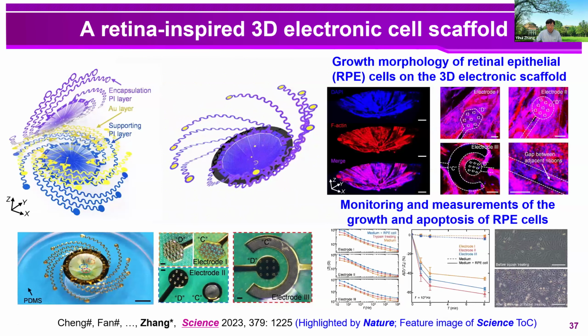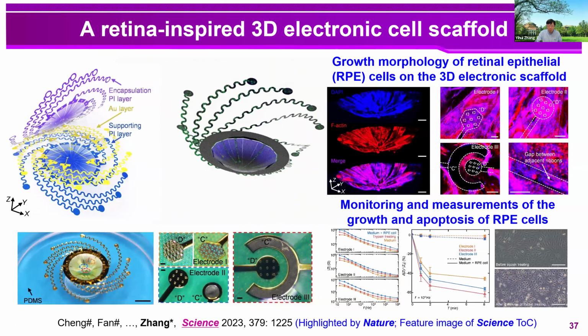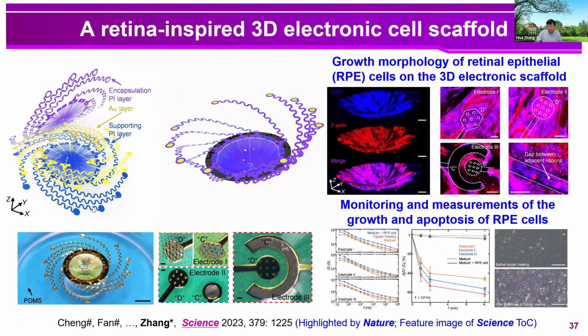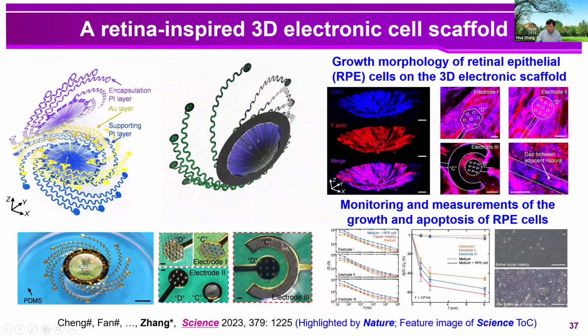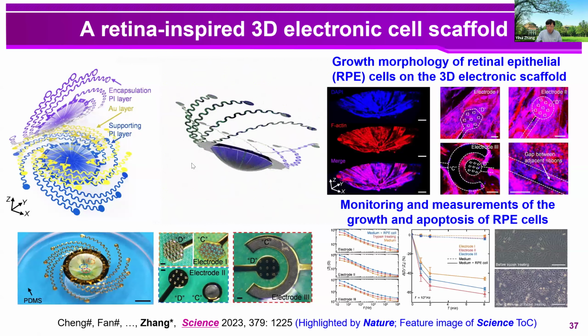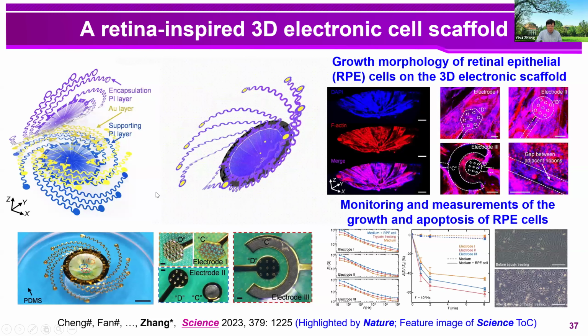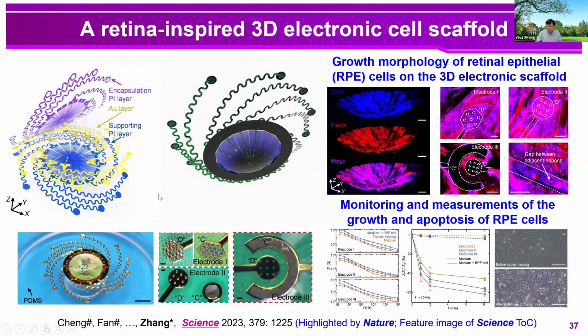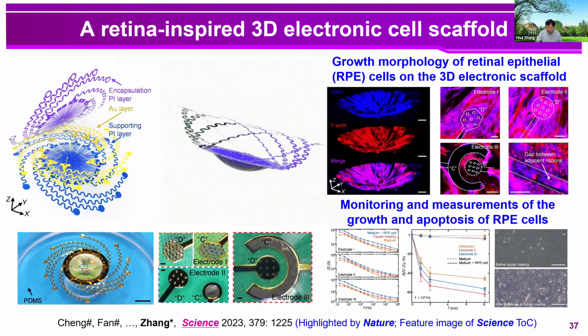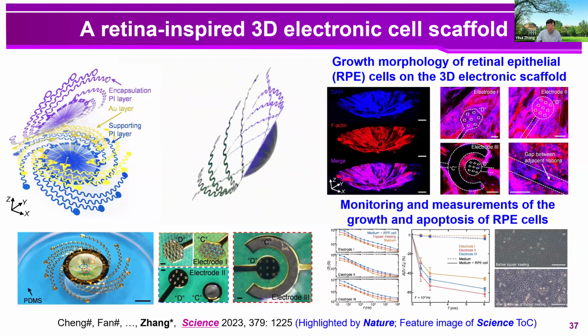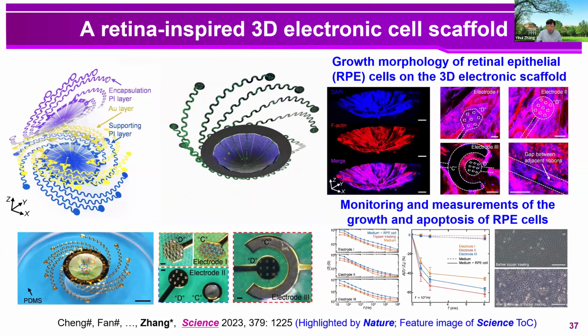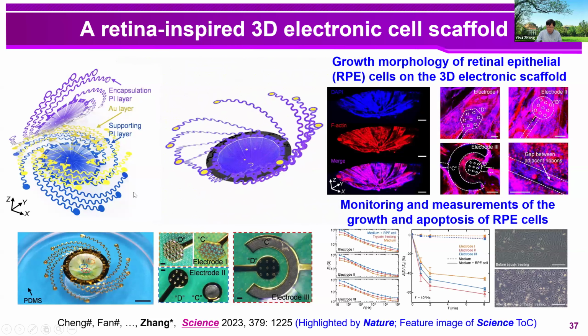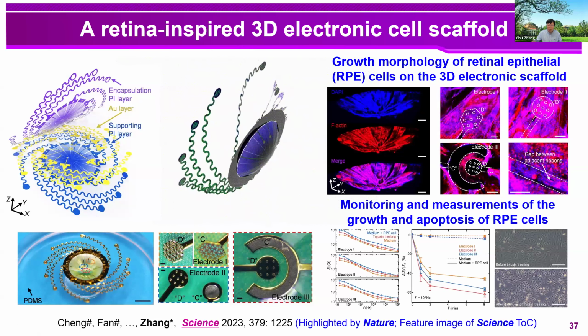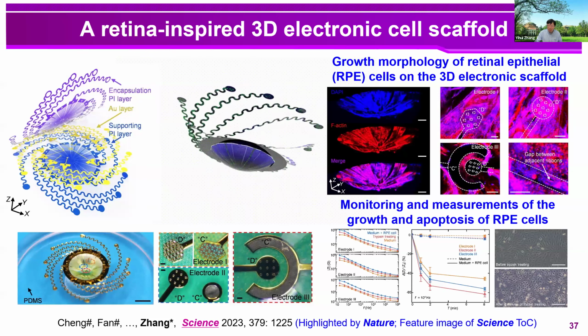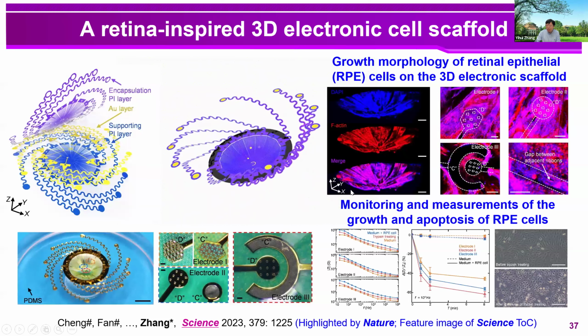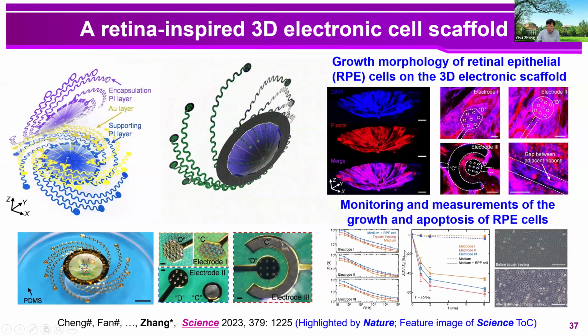So firstly, this kind of microlattice design allows us to construct 3D electronic systems with desired 3D shapes. And here is a retina-inspired 3D electronic cell scaffold. In this example, we can develop a spherical cap-shaped electronic cell scaffold with integrated sensing capabilities. And actually, there are many publications on cell scaffolds based on 3D printing. But these previous studies cannot integrate electronic components on the 3D printed cell scaffolds. So here in our work, the developed electronic cell scaffold can not only provide a support to grow the RPE cells, but also enable the quantitative monitoring of the growth and apoptosis of the RPE cells during the growth through the impedance measurements, as shown here.